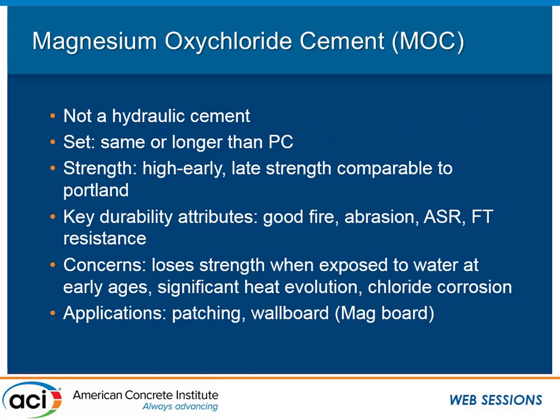binders. So magnesium oxychloride cement: magnesia and magnesium chloride combined with water, and you end up with a really good patching material. There are some issues losing strength when it gets wet early on, but good fire, abrasion, ASR, and freeze-thaw resistance.